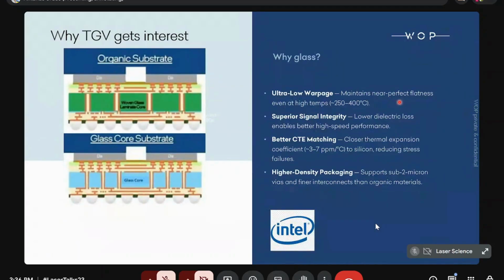The dielectric loss is much lower than in plastic. And you can select glasses which match very well with silicon, meaning that if you place your silicon chip on this glass core substrate, the thermal expansion is the same. You don't lose the contact. You don't have bigger electrical losses in this package. And of course, one very important thing is that glass allows much higher density because of being able to provide a couple of micron wide interconnects between layers.